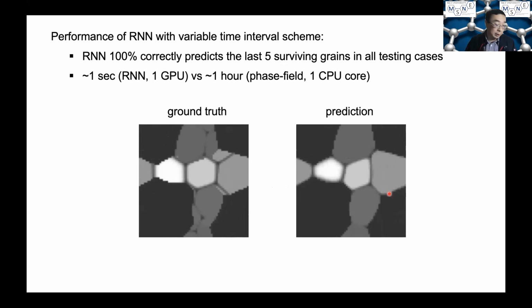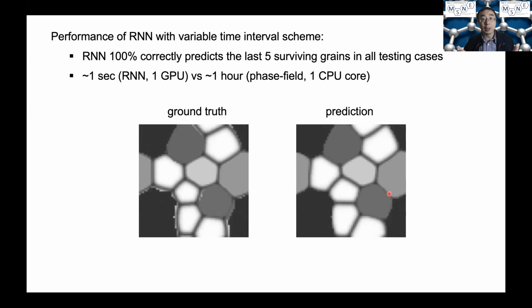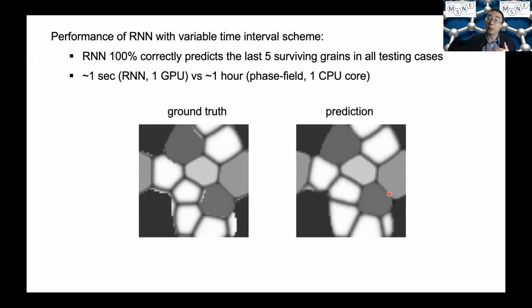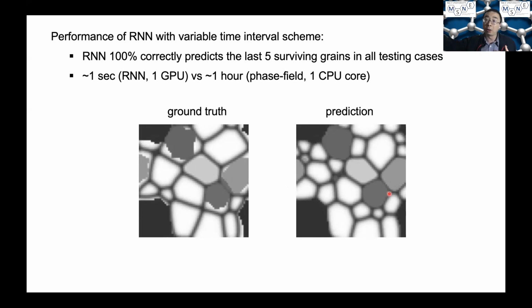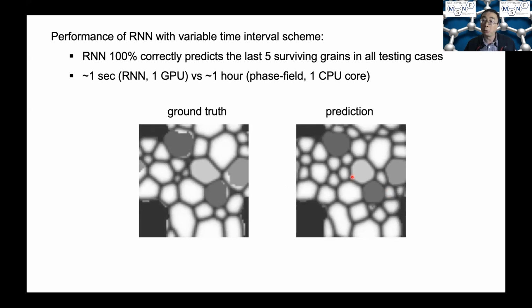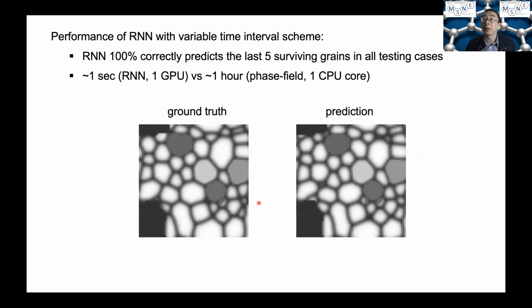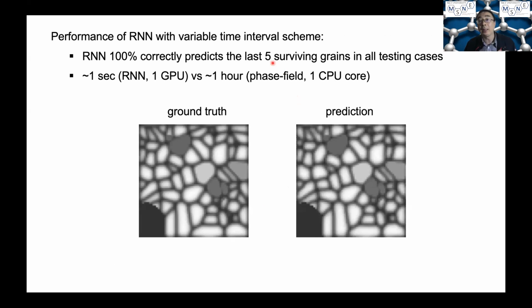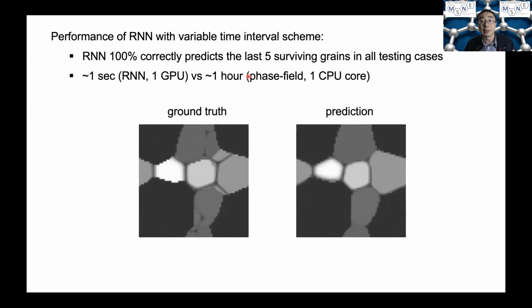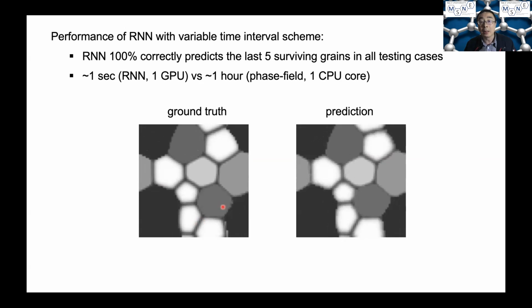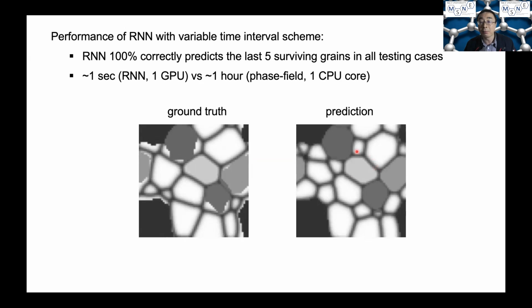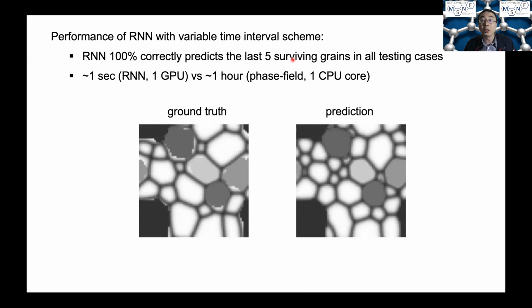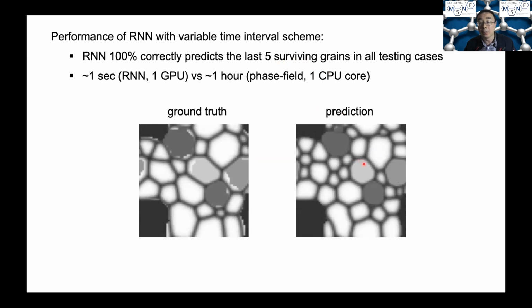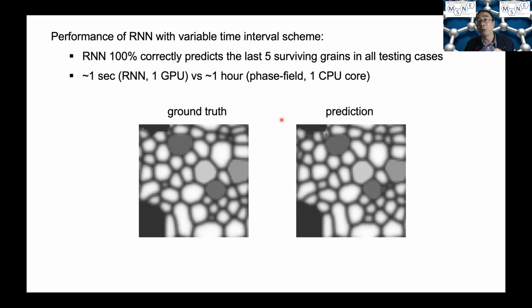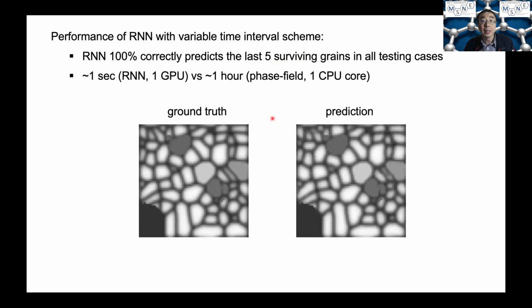Right? And in a more recent test, we even use a variable time interval scheme to allow the machine learning to make predictions at larger and larger time intervals, which is kind of similar to the adaptive time stepping in PDE solvers. And this allows us to further accelerate simulation, while maintaining the accuracy in the prediction. So for example, when we start from 80 grains and let the structure coarsen until the last 5 grains, the machine learning is able to predict correctly which 5 grains will survive with 100% accuracy in our test.